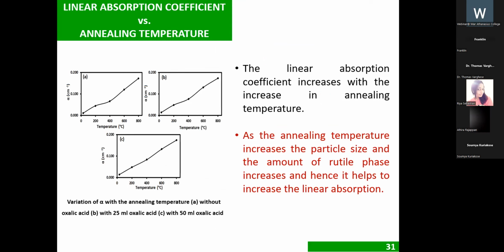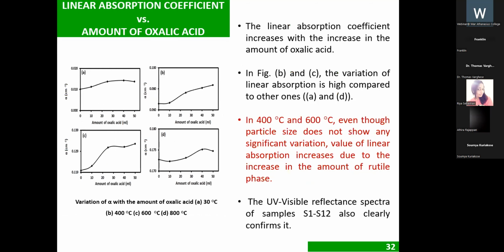As the annealing temperature increases, an enhancement can be observed in alpha, because of the enhancement in particle size, which helps to increase the value of alpha. And when we plot alpha against the amount of oxalic acid for each annealing temperature, there is a change in all cases, but the maximum change can be observed in B and C, because in B and C there is a transformation from other phases to the rutile phase of TiO2.